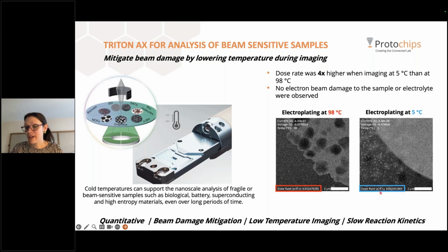Because if we used this dose rate at the higher temperatures, what would have happened is we would have de-wet the cell. We would have pushed all the liquid out of the cell, or we would have automatically started crashing out electrolyte or crashing out copper from the electrolyte from our different experiments. And Kate's going to cover this experiment in a little bit more depth, but using our dose module, we were able to understand and review the dose data and see that even during our experiments, which were not in-depth research experiments, you could see the initiation of the fact that the cooler temperatures really do help mitigate some of the damage that the beam can cause.